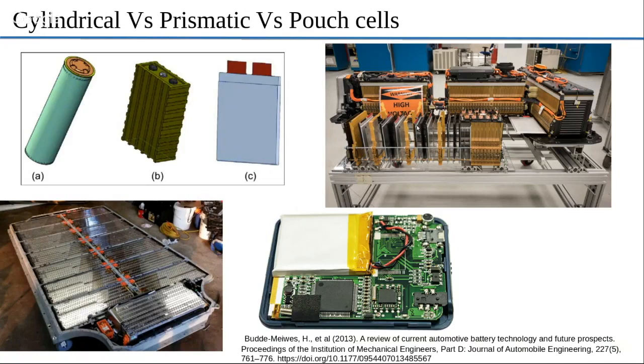You can supercharge your Tesla, even though Tesla recommends not supercharging your car every day. But if someone were to only supercharge their car, it is still less than 1C or close to 1C. Less than 1C is not going to degrade your chemistry.